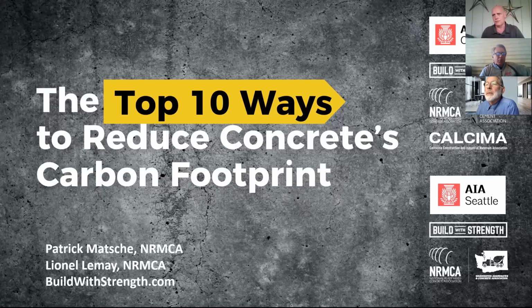And that's why I propose this idea of providing a carbon budget, because now the contractor and producer team can say, okay, listen, we need a mix design that has a carbon footprint that's higher on the slabs only because we have these other performance criteria, finishing, post-tensioning, higher strength, whatever. But we're going to go to the other limit with a really low carbon footprint on things like the mat foundation, the shear walls, the columns, and everything else. If you try to limit carbon footprints for each individual mix design, if you do provide those limits, then you may force a sticky concrete, because the producer and contractor have no flexibility to meet that requirement. Yeah, well, that's part of the discussion, workability.